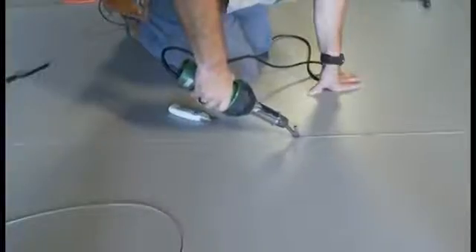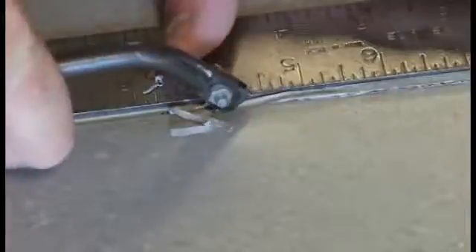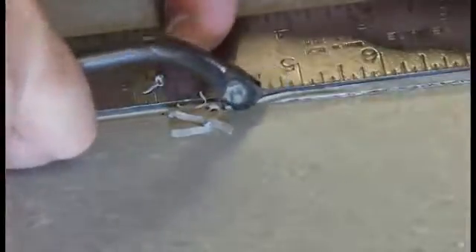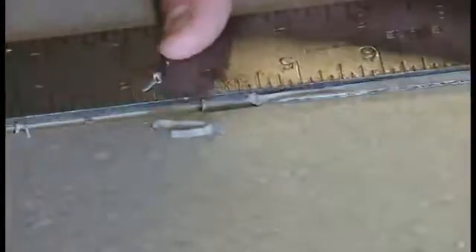Once the first part of the seam is welded, you will need to change directions. Make a ramp by skiving the weld rod 1 to 2 inches from the end of the welded seam. Hand groove the skived section of the weld rod. From the opposite direction, continue welding up the ramp and overlap the initial weld for several inches, creating a splice.